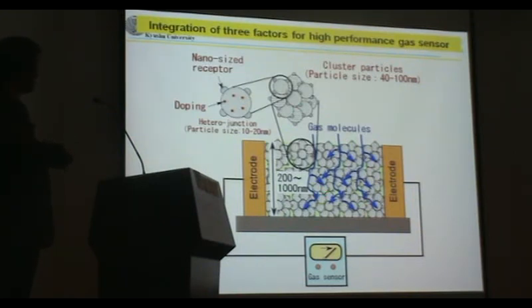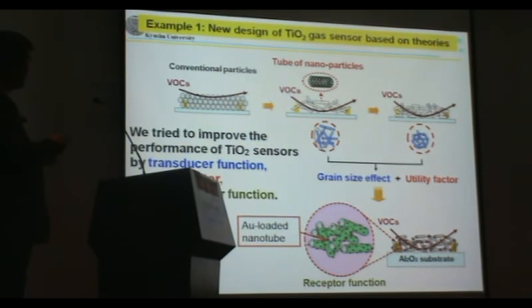Finally, for all of the particles, the resistivity changes drastically. I'm going to show one example. This is the VOC sensor. We prepared a nanotube consisting of nanoparticles. This is a very small particle, and these particles formed a nanotube. We deposit this nanotube on the alumina substrate and load gold nanoparticles like this. Finally, this sensor can detect VOC in the sub-ppm level.